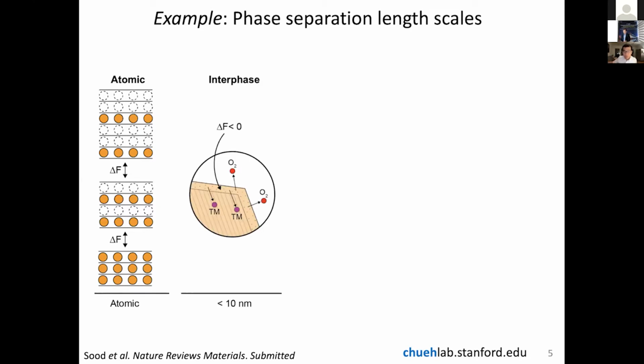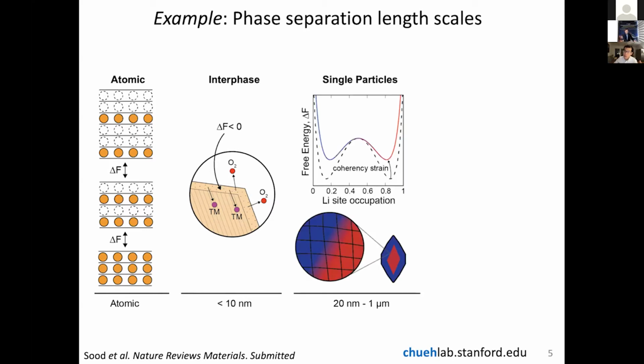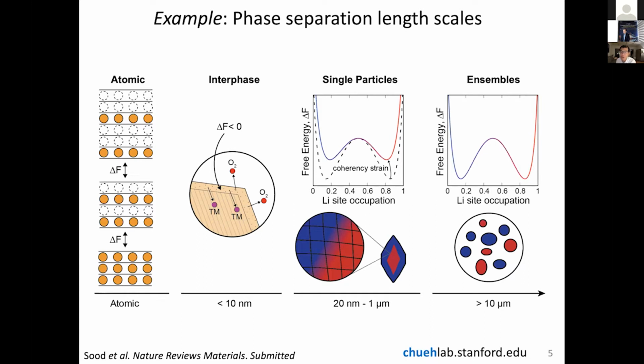You can then move up one length scale to a few nanometers, and this is a situation of surface phase separation, where, say, the surface of a particle could have a different phase than the bulk, driven by interfacial free energy. Then you can go to the scale of single particles, which could be from tens of nanometers to microns. And here you could have phase separation, and you have, say, compositionally rich and compositionally poor phases driven by the double well free energy. And you can even go to ensembles where you have many particles.